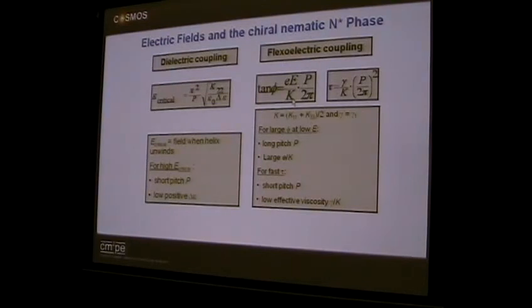Okay. Right, so when you look at the electro-optic effect in flexoelectric coupling, this is the flexing of the spring, think of it that way, then the angle phi you rotate through, to a good approximation, depends on the pitch of the helix, and you can imagine that if you have a tight helix, it's harder to unwind, okay, and the elastic constant. The response time, and this is peculiar to the flexoelectric effect, does not depend on the field you apply. Whatever voltage you apply, whatever field you apply, the response time to a first approximation is independent of the voltage. That again is unique.